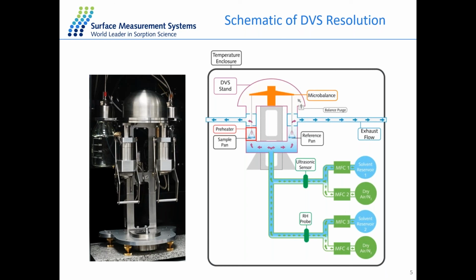Another question here: can you do gas sorption with the DVS method? With the instrument I introduced today, there is a flow system with a carrier gas, which is nitrogen or air. This instrument cannot do gas sorption, but we do have a vacuum system that uses a vacuum pump and only measures the sorption of the molecules by pressure. In that case, we can do any kind of gas sorption, like CO2 sorption, SO2 sorption, or hydrogen sorption. So if you're interested in gas sorption, we can give you more information about our vacuum system.